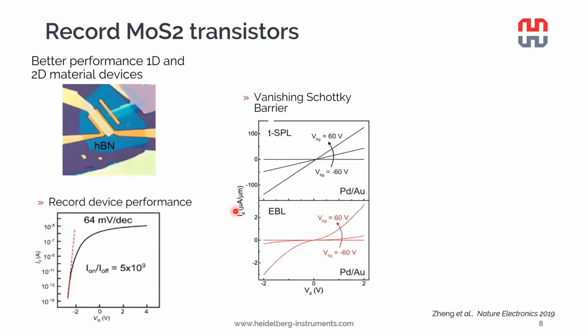The paper reports record device performance with an on-off ratio of 5 × 10⁹ and extremely nice subthreshold swing. What is most notable is that the Schottky barrier is vanishingly small, shown here. For the NanoFrazor patterned device, it's completely linear over a very broad voltage range, while for the electron beam lithography fabricated samples with identical electrode material and geometry, we see very coarse nonlinearities.